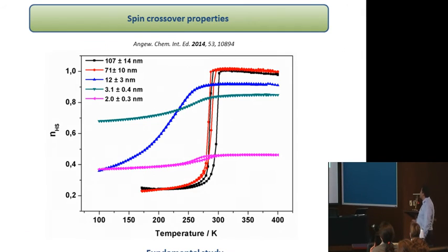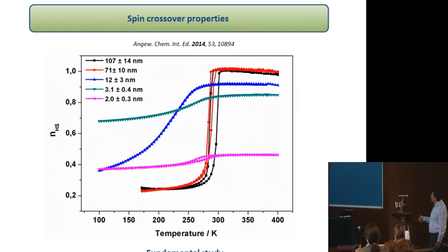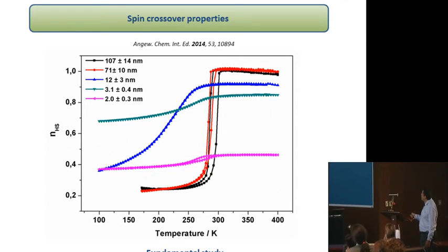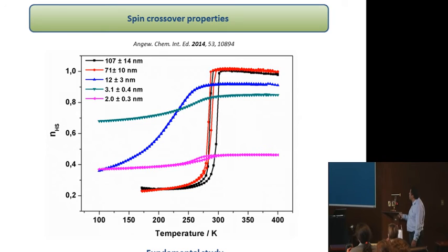Okay, so now if you look at the properties of these different samples, different particle sizes. For large nanoparticles, of course, we have a lot of molecules, so you have big interaction. So as expected, you have a spin crossover with hysteresis at room temperature. When the size decreases, for example, at 10 nanometers, as expected, we have a decrease of the transition temperature, and the cooperativity decreases. We have no hysteresis loop, and we have a gradual transition. This is expected because we reduce the number of iron centers. So you decrease the cooperativity, and you have a gradual transition.